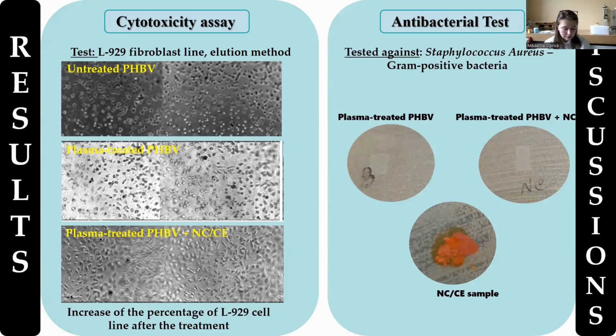For the moment, the tests regarding the antibacterial activity of these dressings were carried out only for the PHBV and for the plasma-treated PHBV and the plasma-treated PHBV containing cellulose, where no antibacterial activity was recorded, as expected. And below we have the nanocellulose sample containing curcumin, presented in another slide, where we can see that it has a slight antibacterial effect that can be expected from the film.